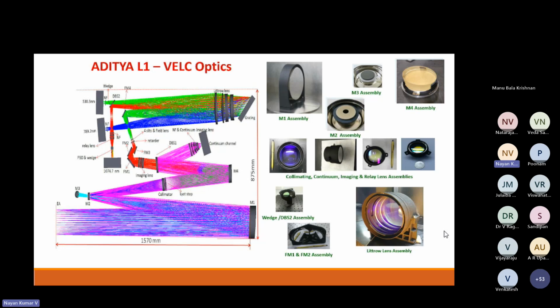The reason is that material mismatch also creates a problem. Suppose we go for some other coating. CVD is a silicon carbide coating over silicon carbide, so it has a very good match. If you go for alternate layers, there are some instabilities. But it takes a lot of time to do. Time is one factor. The yield also is very poor. Out of some 20 blanks, you may get 1 or 2 blanks, and each run costs around 10 lakhs. One coating run is around that.